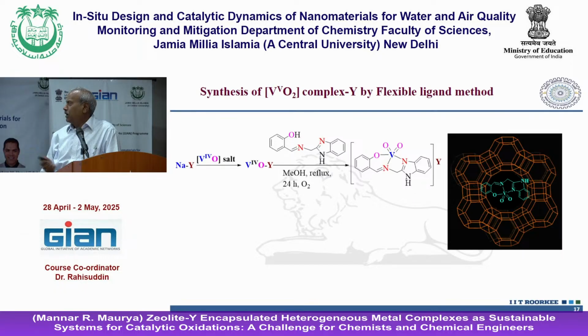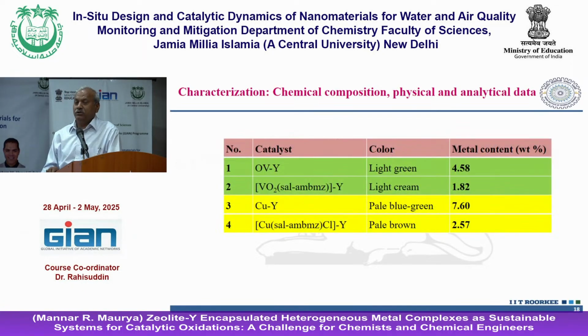in the IR. Now, how to characterize? That's the question. When you have ICP-MS, you can find the metal content. Through FESEM, you can find morphology and also the metal content. Through TGA, you cannot find metal content here, because you have alumina and silica. Silica is highly stable; when you heat it, it will not decompose further, right? So metal content determination through TGA is not possible here. The only possible way is through ICP-MS.